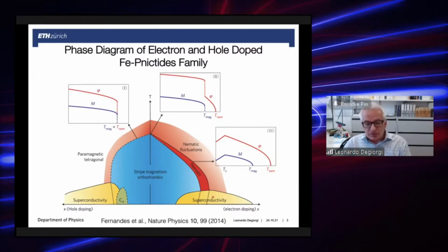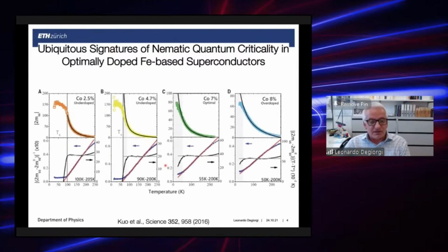Now, with respect to the nematic phase transition and nematicity in general, the DC transport properties, and actually the anisotropy induced by an external symmetry breaking field in the DC transport properties, were of paramount importance in order to shed light on nematicity. In fact, by measuring the DC anisotropy when you apply uniaxial stress, so by performing an elastoresistive type of investigation, you can extract the nematic susceptibility, which is shown here for the family of the cobalt-doped 122 materials from the underdoped all the way up to the optimal and overdoped regime.